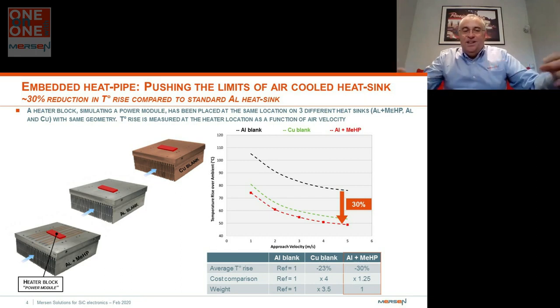So it helps with spreading the calories over the base plate, and by embedding those heat pipes inside the base plate, we can easily demonstrate that we decrease by 30% the temperature rise just underneath the module. So rather than heating with a lot of hot spots, we can really decrease it, and we can show that for only probably a 20-25% increase on the cost, we can really get more than 30% efficiency gain compared to a very basic heatsink. So this is for the air cooling.